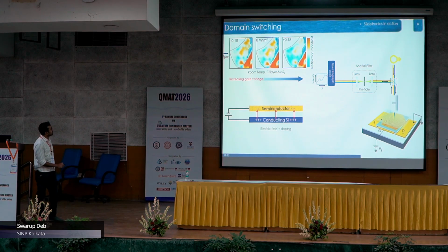You see, in the central panel, when there is no voltage applied, I can already see a few domains. They are false colored in orange and turquoise blue, if you wish. Now when I change the gate voltage, this orange colored domain shrinks in size at the expense of the blue colored domain. So this is very much similar to how a domain would shrink or increase in size in the presence of an external field, similar to any magnetic material or ferroelectric material.